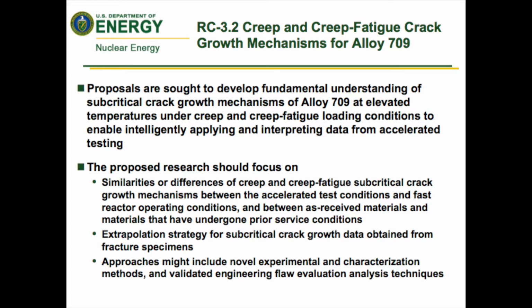That sodium compatibility is also a key for the application of this material. So therefore, that 709 sort of have overall capable performance. Yeah, I forgot. Considering that one of the principal applications of this alloy would be for sodium fast reactors, sodium compatibility is clearly one of those multiple characteristics we wanted to make sure we did maintain in moving forward with this material. That's not a requirement for the ASME code, but it is a requirement for the potential application we're looking for. Do you have any concerns about environmentally assisted cracking or stress corrosion cracking for this alloy system?